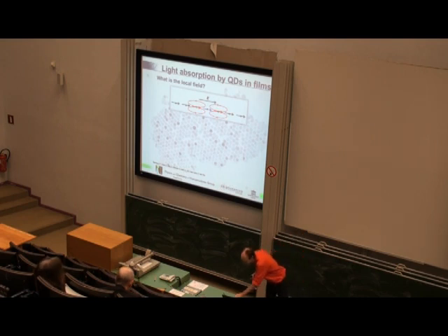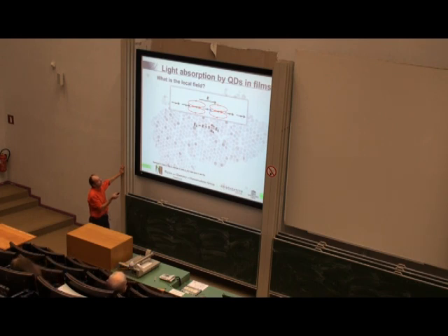And so if we want to express the field driving a single dot, this blue one for instance, we have the optical field, that's the first E term, and then we have the contribution from the neighbors. There's a number of terms there, they're not so important. This dipole that you create will of course depend on the material you have at hand, and that determines this alpha O. The S tells you something about the influence of the distance between the dots, because if the distance is larger, this field will be smaller, etc. So there's a material term there, and there's a kind of configuration term in there.